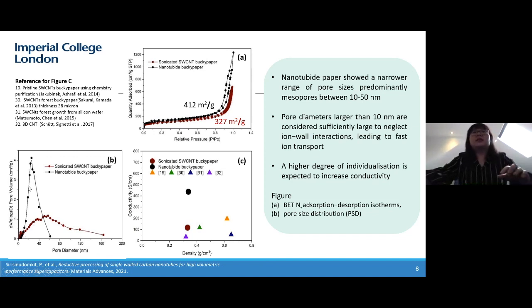And in the study, it showed that a pore size larger than 10 nanometers can be large enough to ignore the interactions between ions and the pore walls, which means the pore can be big enough to improve ion transportation, while the micropores from the sonicated SWNT bucky paper give poorer ion transportation, leading to lower power density in the electrochemical system. And for the conductivity values measured through four-point probe measurements, the nanotube bucky paper achieves a higher conductivity compared to other CNT-based bucky paper, including the sonicated SWNT bucky paper here, which proves that a high degree of individualization is expected to increase the conductivity.